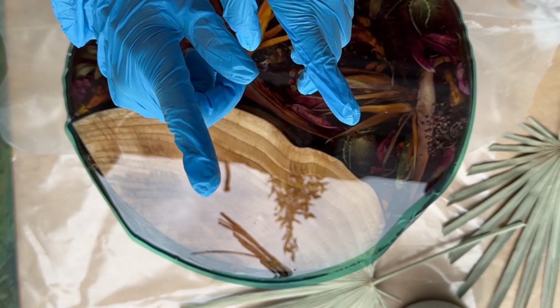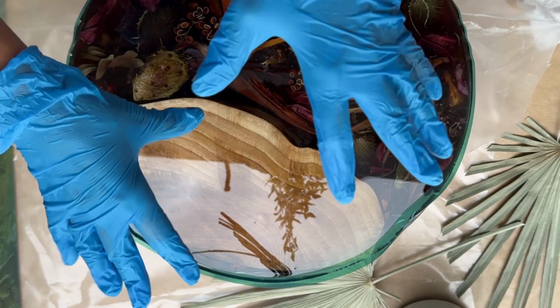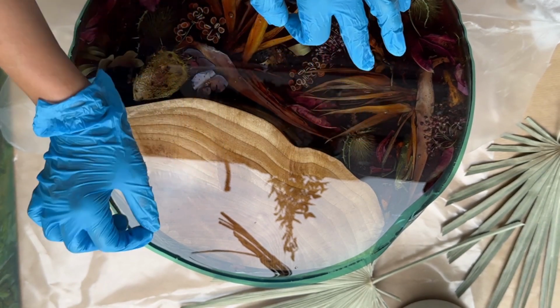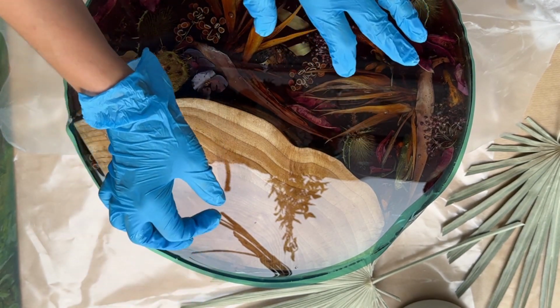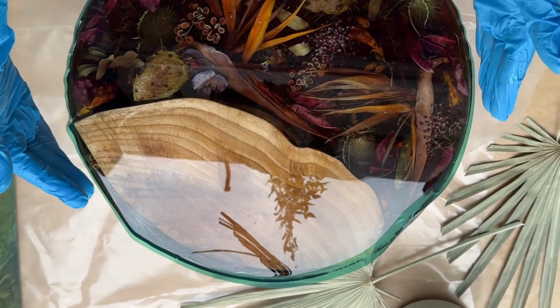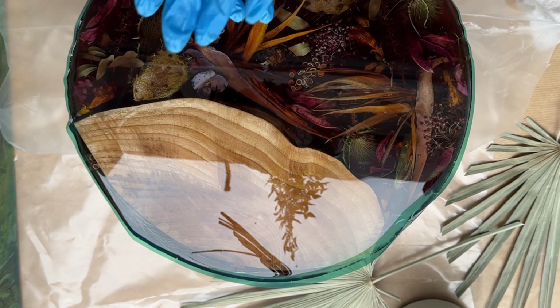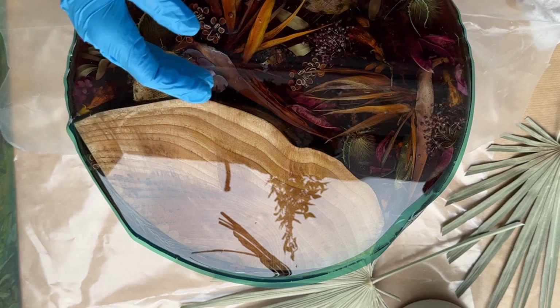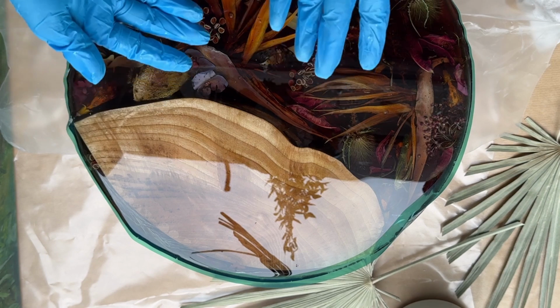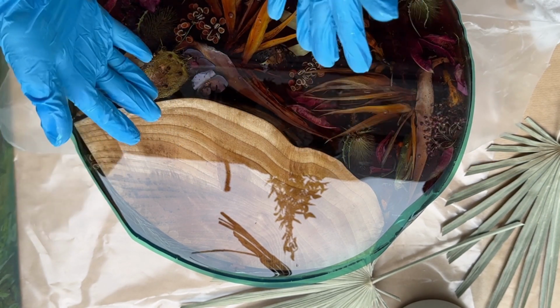If we're talking about an artistic resin, we give it literally 10 minutes to settle, then wrap it in tape and pour. We wait right here and check the viscosity of the resin with a toothpick. When it stretches like honey, we remove the tape and it spreads over all our edges. We help with our hands, a burner, a hairdryer, whatever you have. We remove the tape, the resin will spread, and it gives us a caramel edge. That's where the secret lies, but choose the right resin. I generally wait before removing it.